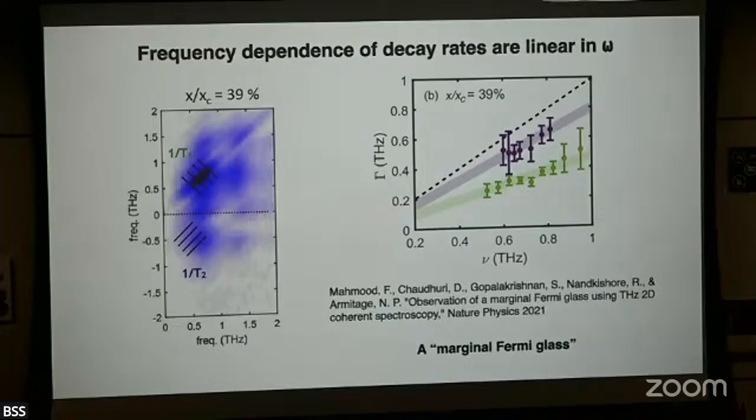You know what I guess is that things like weakly interacting Anderson insulators, they provide us perhaps a cartoon for understanding the physics. Disorder is important, which influences localization. But the model that I have of what's going on here, and I think this is ripe for a lot more theoretical thinking, is that we have the elementary excitations, these localized dipoles, and those dipoles can lose energy, and the energy can diffuse and move out through the lattice through this resonant dipole coupling. And so what is that thing that is there in the end? Well, it's kind of an overdamped version of what it already was, a dipole.